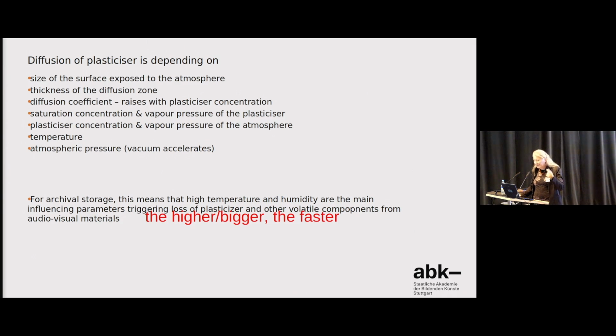The diffusion coefficient rises with the plasticizer concentration, so it depends a little bit on the production of the material, the saturation concentration and vapor pressure of the plasticizer inside the molecular system, and the plasticizer concentration and vapor pressure of the atmosphere outside, which means high temperature, high humidity, high vapor pressure, high evaporation. Temperature and atmospheric pressure, which means that vacuum accelerates this process. So vacuumating your items is not the best thing. Or you have to decide what you want. You have to die one death. The question is, which one? The higher this factor, the faster they proceed.